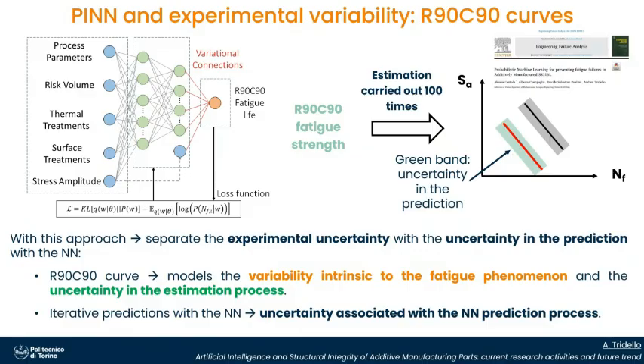Okay. The R90C90 curves, which have been considered in the training dataset, model the variability intrinsic to the fatigue phenomenon and the uncertainty in the estimation process, since we can have a dataset with less data. The iterative prediction with the neural network models the uncertainty associated with the neural network prediction. Okay, so this is very good for fatigue, since we start from literature data, and we can have variability in the prediction.